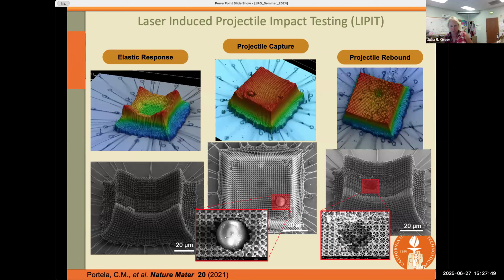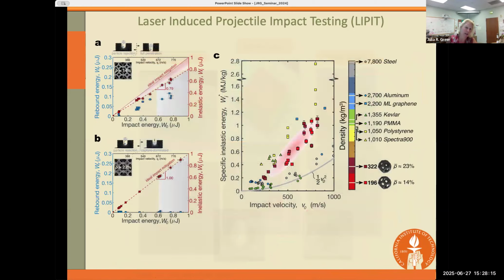And the 3 types of response that we observed were elastic response, where the projectile fully rebound, projectile capture, where the projectile was embedded, and then projectile rebound. And that is where it left a crater, but it rebounded back. What we never observed was any kind of behavior where the projectile penetrated through to whatever this nano-architected layer was protecting. So this is a very promising impact mitigation strategy.